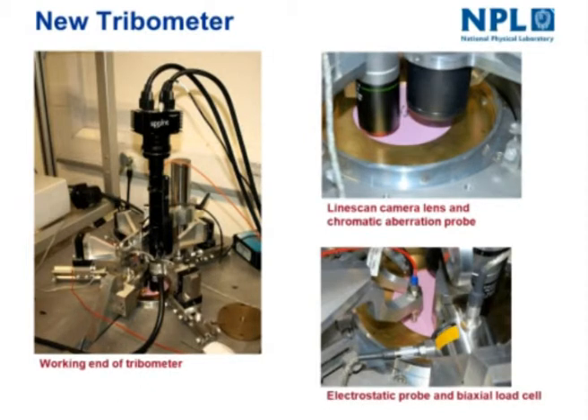And in actual fact, we could have one image of the wear surface that gives you a complete time history of the wear surface during a test. And that's the important thing. This is online, real-time examination of the wear surface. It's not in situ, because that would mean looking through one of the test samples at the wear surface on the disc. But we're also developing techniques to do that, actually, using sapphire probe.